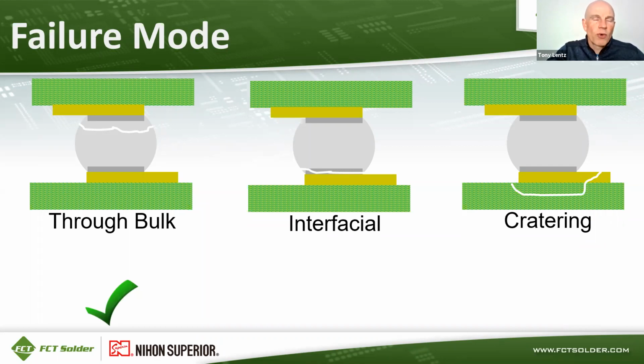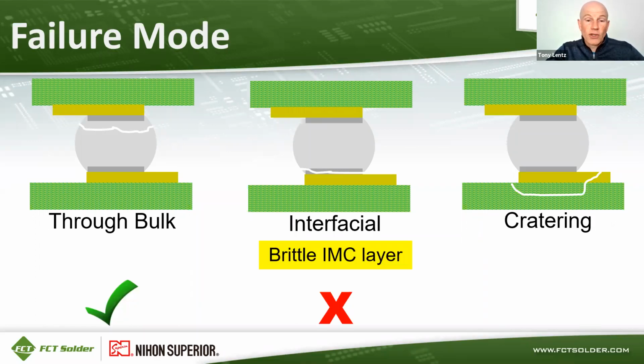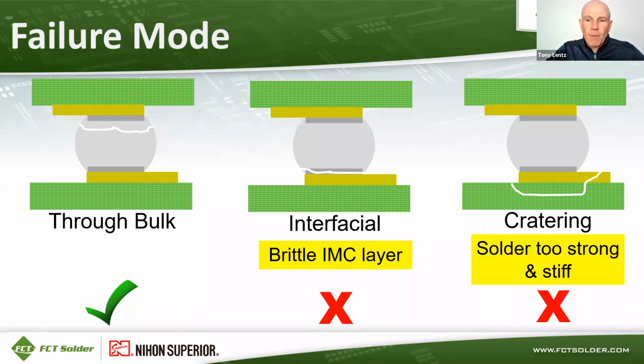Of course, if that circuit board's out in the field, any failure is not necessarily ideal. It's not desired. But through the bulk means that you didn't rip apart your circuit board or your component, and it's not due to intermetallic growth and embrittlement over time. So interfacial failures are usually due to a brittle IMC layer, which thickens over time. And that's undesirable because that's uncontrollable. You don't know when that's going to happen.